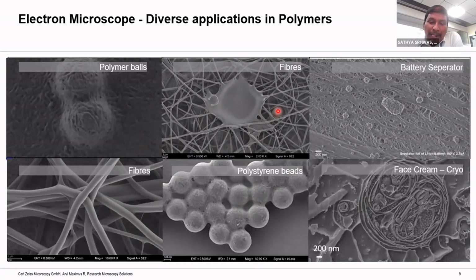You can see the depth of focus here is much greater in the field emission scanning electron microscope. When you focus on a particular part, the other fibers underneath the particular fiber are also in focus. That is a help compared to a normal optical microscope or a basic conventional SEM. The depth of focus is much higher with the field emission source, which helps you understand more surface information if there are freely suspended features, because one end of this fiber is suspended here, but the other end is not, and still you are able to resolve the surface information clearly.